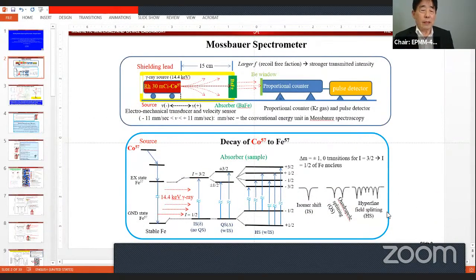You're looking at the Mossbauer system here. This Mossbauer system consists of a gamma radiation source, the sample here, and a proportional counter. That means the analytical tool observes the gamma ray through, for example, the barium ferrite right here. Once the cobalt isotope decays to the ground state, you expect a 14.4 kiloelectron volt gamma ray. This gamma ray hits the sample, some energy is absorbed, and the transmitted energy is detected proportionally with the pulse detector.